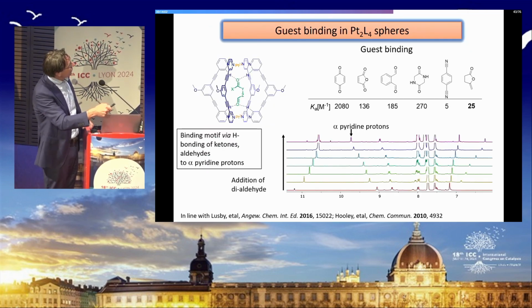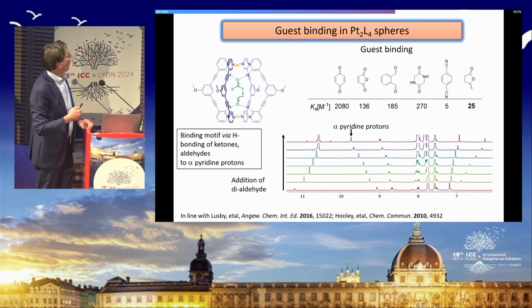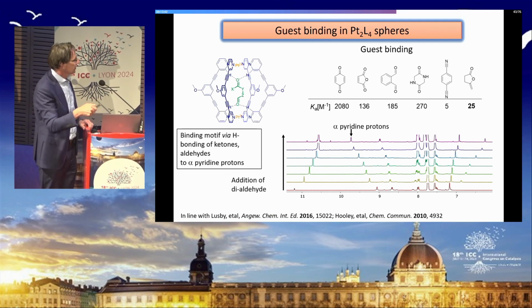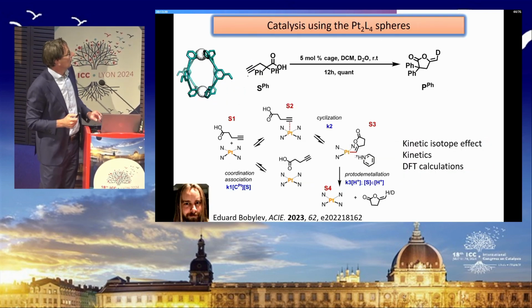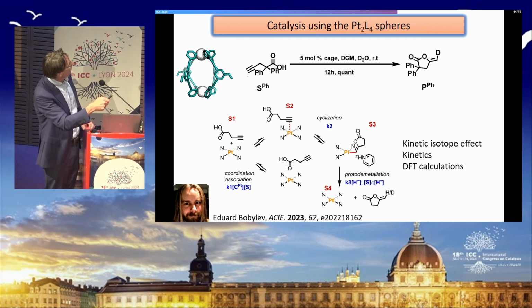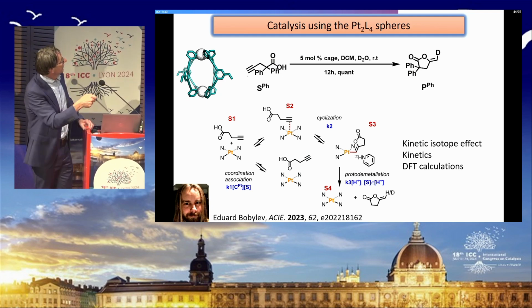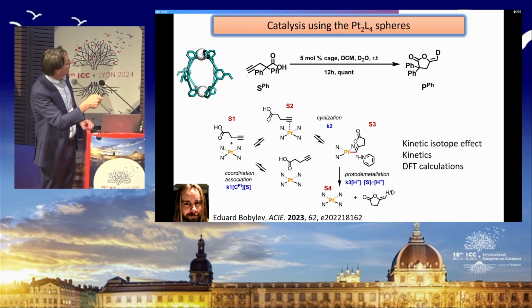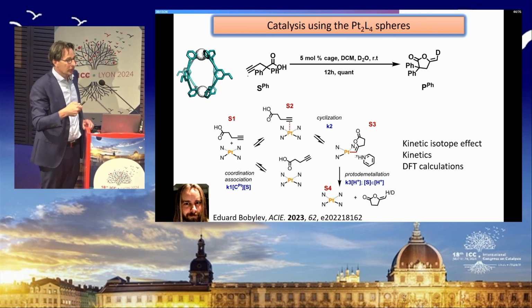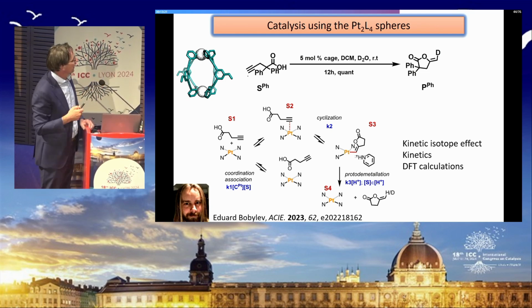So we did guest binding studies, and these diketones bind quite nicely, depending on the shape. Obviously, nitrile binds, but very weakly, and also this cyclic compound does bind. And binding occurs via hydrogen bonding with the CH next to the pyridine and the carbonyl, in line with what others have reported as well. Next, we looked at the cyclization of this alkyne acid to form this 5-membered ring. We on purpose put phenyl substituents on this, because then the substrate is too large to bind in the pocket, so the reactivity is only at the outside.